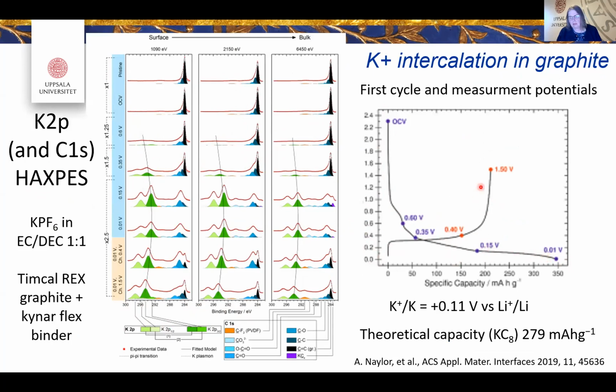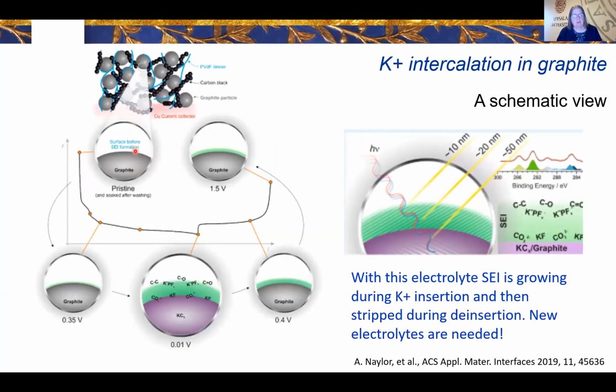And you can already, by the cycling curves, say, oh, we have a large capacity loss during the first cycle. Yes, we have. And why is this? Well, we have the graphite, we insert the potassium, you get an enormous SEI layer. But even worse is that it's actually shrinking a lot again when you are removing the potassium, which means that when you take your second cycle, you actually have to form this again. It's taking a lot of potassium again for the second cycle. And with this kind of technique where you do depth profiling, we can say a lot about the composition and depth profile of this. In this case, it's so dramatic that we can have a very simple conclusion: newer electrolytes are needed. They are really important.